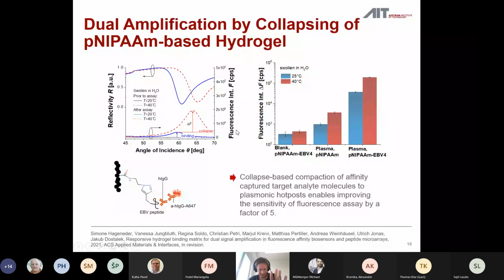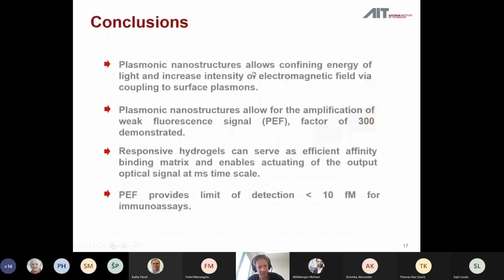Eventually, this slide illustrates a dual amplification strategy in the readout of the assay based on fluorescence spectroscopy. We use the optical enhancement seen here as these peaks in the fluorescence signal associated with coupling of light of the excitation beam to the surface plasmons. Then, if we trigger the collapse of the gel in which we capture the target analyte, we see that the strength of these peaks further increases by dragging the molecules closer to the surface, where they can be more efficiently plasmonically amplified. You can see that this factor was about 5, which we could put on top of this 300 I mentioned before. Again, I probably don't have so much time to go into details, and this drives me to the last slide.